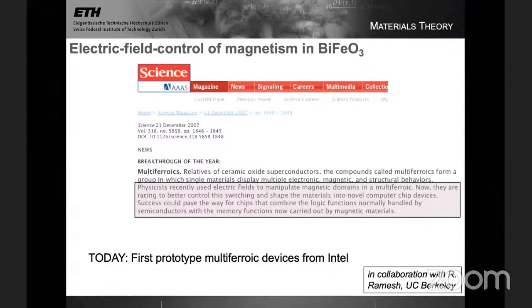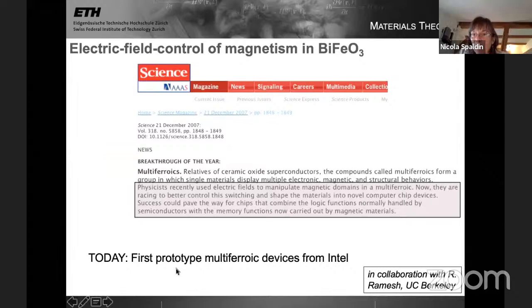Is this Intel device using bismuth ferrite or something else? It's using bismuth ferrite exchange coupled to, I think, cobalt. They exchange bias cobalt onto the top of the bismuth ferrite, because then they introduce the ferromagnetism. So when they switch the ferroelectricity, they also switch the anti-ferromagnetism in the bismuth ferrite, which then switches the ferromagnetism in the cobalt.